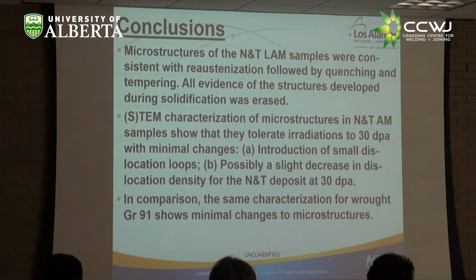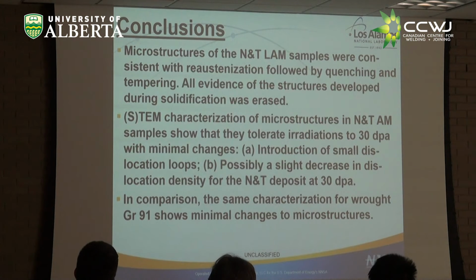Okay. The normalized and tempered was consistent with anything you would expect to happen. And as I mentioned, typical of steels, when you do the normalizing and temper and you do it in a slow way during heat treatment, all evidence for the solidification microstructure that remained in the as deposited were erased.